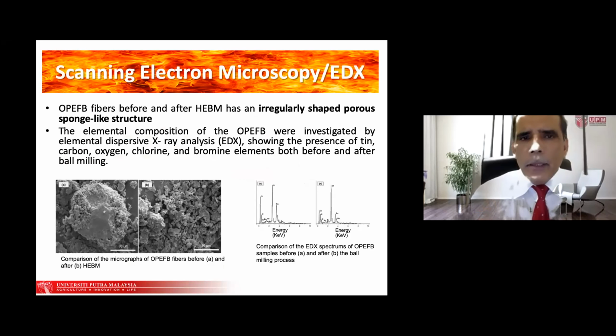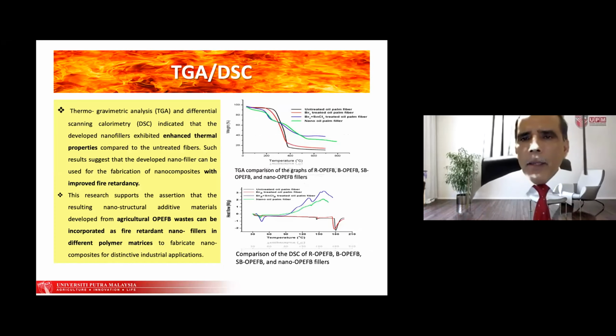And on the left side, we looked at the comparison before ball mill and after ball mill. We investigated the EDX, showing the presence of tin, carbon, oxygen, chlorine, and bromine elements, both before and after the ball mill. And we also did the TGA and DSC of these materials, and we found that the resulting nanofiller can be used for the fabrication of nanocomposites with improved fire retardancy, and can be incorporated as fire retardant nanofillers in different polymer matrices to fabricate nanocomposites for distinguished industrial applications.